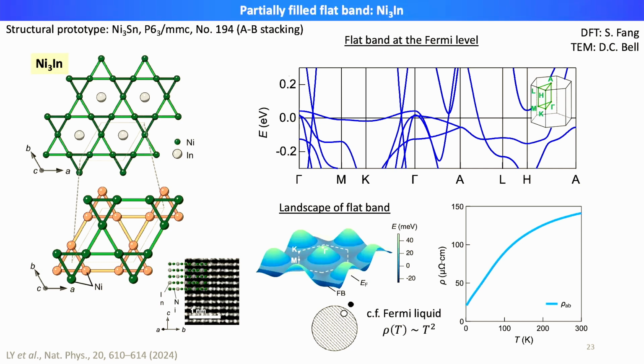In the plane, you can see that these electronic states are indeed partially occupied, at least from the DFT perspective. So we were first quite excited to see these flat electronic states in DFT, and we went to the lab and tried to measure the transport properties of this material. And this is what we find.